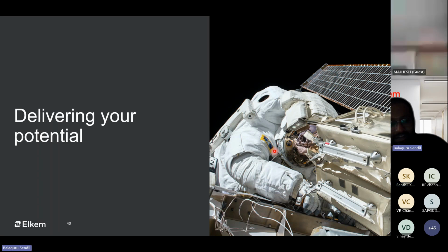Slag as such is a very, very complex thing. For slag itself, I can present a separate session for 2 hours. But we do a lot of slag analysis from different locations in the foundry: from the furnace, from ladle lining sticking, from the pocket. So we can check what the slag is. It is acidic, neutral, or basic. Based on that, we can classify whether it is a slag or a dross. A lot of things we can check. You can send us the sample.